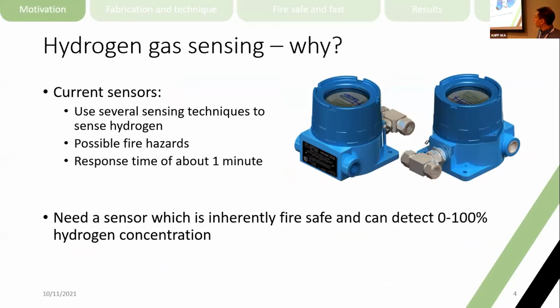However, hydrogen gas sensing is actually not new. That goes back quite some time. However, the current commercial sensors are not quite up to the task. The current sensing techniques, for example, don't cover the full concentration range from near 0 to 100%. They typically use 2 sensing techniques to cover the whole concentration range, and this commercial sensor shown here uses, for example, a capacitive measurement and a resistive measurement on a nickel-palladium alloy.